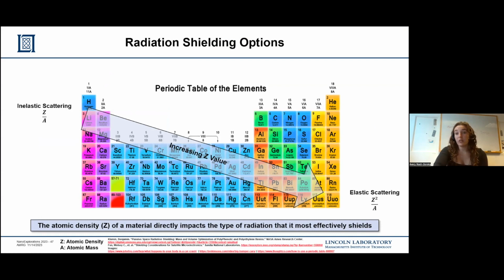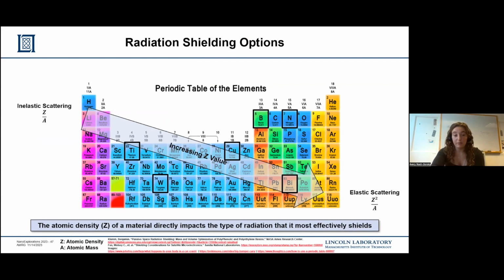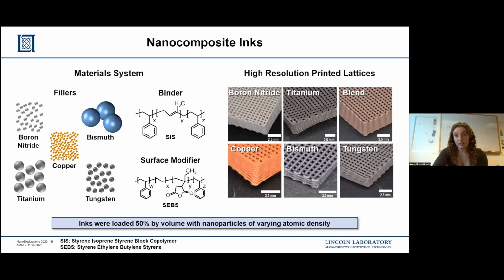So when we chose to select our nanoparticle fillers, we did these with elements varying all over the periodic table. Looking at our material system, our nanoparticles include anything from our low Z material, boron nitride, our mid Z nanoparticle fillers, which are titanium and copper, and then we have our high Z materials, which are tungsten and bismuth. However, it's important to note that even though bismuth has a higher atomic number than tungsten, it has a lower bulk density, which means that tungsten behaves as our highest Z material.